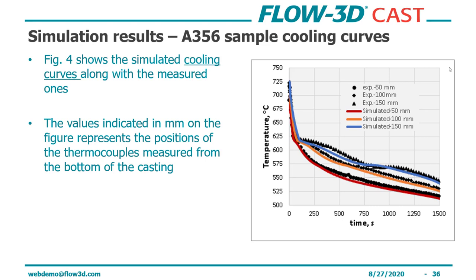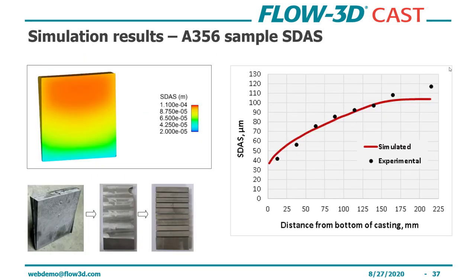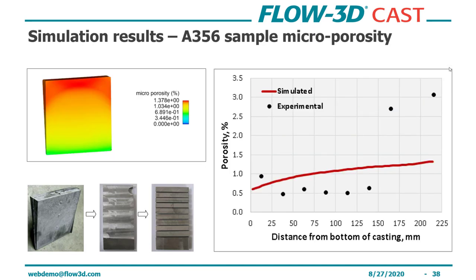You also need some foundry-specific data for your mechanical properties. You can either use strength coefficient K and strain hardening exponent N, or alternatively use witness sample data — witness sample elongation, witness sample yield strength, witness sample ultimate tensile strength. If you have samples from your process with mechanical properties, you can apply those numbers directly. The heat transfer coefficients are completely foundational, so we want to make sure our HTCs represent the correct cooling and temperature profiles at the different thermocouples — that's the first step to make sure we're doing well.